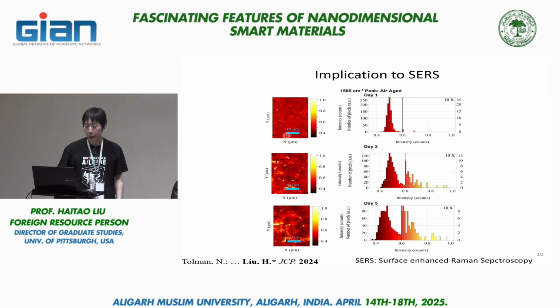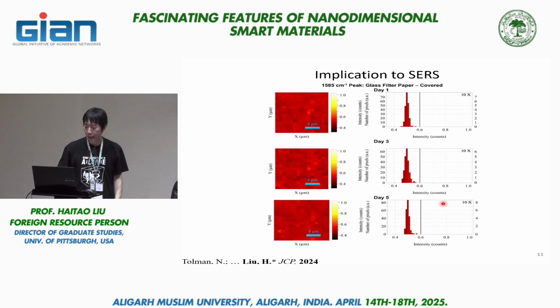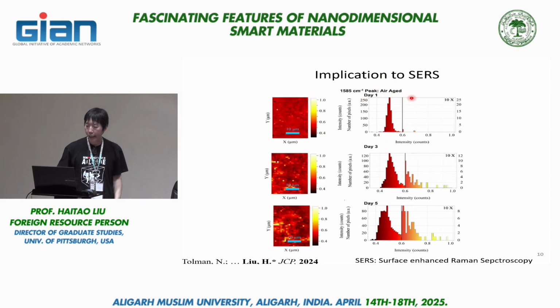So what you see is as you increase the air exposure, you start to see more and more stuff showing on the SERS substrate. And those are aromatic or non-aromatic hydrocarbons being accumulated on the surface and being detected by SERS because the SERS substrate enhances the Raman cross-section of the analyte molecules. On the right-hand side, I show the same kind of statistics, but showing the relative intensity histogram, and you clearly see this high intensity part becomes more and more significant as you expose the substrate to air for a longer period of time. And so this one is aged in air, so we just leave the sample in air and didn't do anything special.